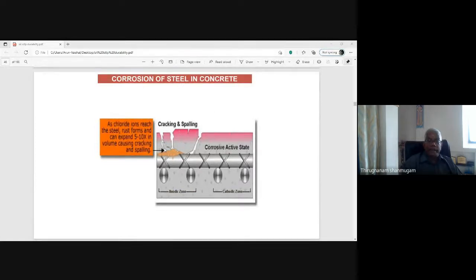Corrosion of steel in concrete. That is the pictorial representation. That is the steel reinforcement. This one is the anodic zone and this one is the cathodic zone. Where a passive film is present, depending upon the ingress, as chlorides reach the steel, rust forms and can expand 5 to 10 times the volume, causing cracking and spalling. These rust products, or corrosion products, cause cracks and spalling of the cover concrete. So water, oxygen, carbon dioxide, or any other external agents easily attack the surface of the steel. The steel surface is not protected, so corrosion of steel takes place, and very soon failure of the structure is expected because of the corrosion.